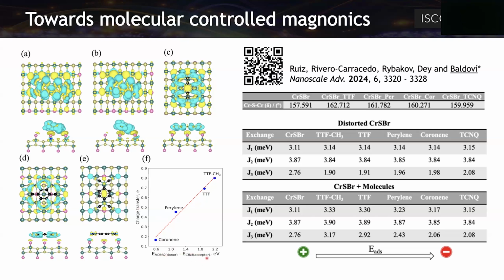And we relate these two properties, the charge transfer from ab initio, and when we plot it versus this energy difference, we can get this very nice correlation. So now, if we have a different molecule, we can calculate the HOMO, and as we know already the conduction band minimum of the acceptor, we can predict more or less how much charge transfer is going to give to the material.